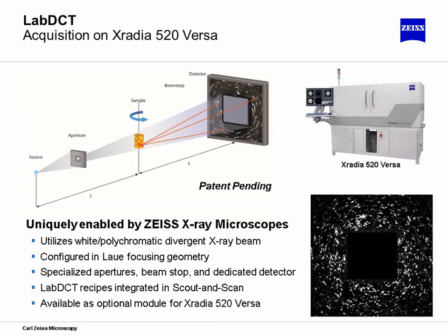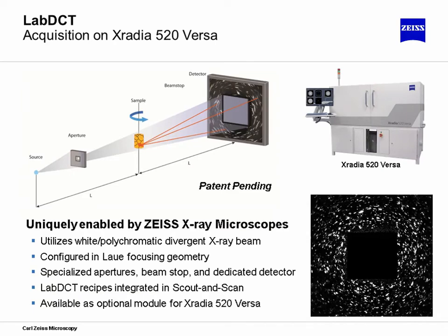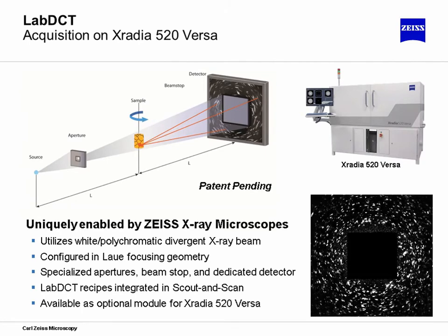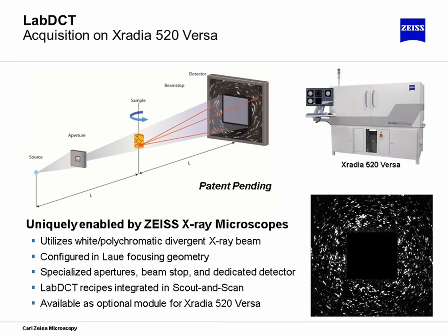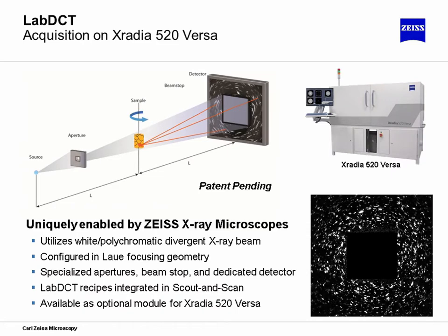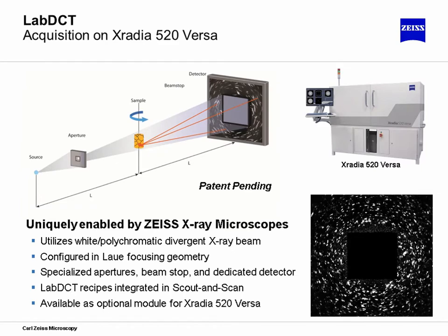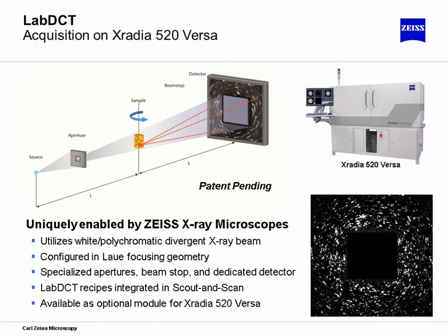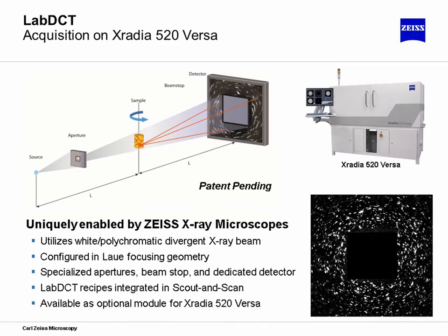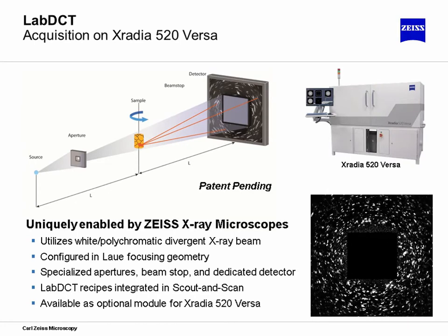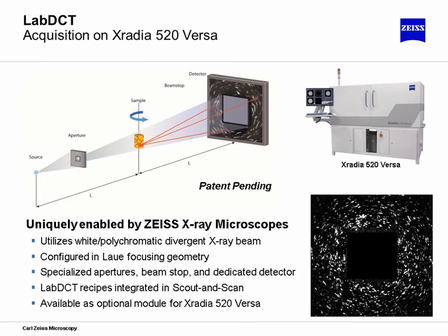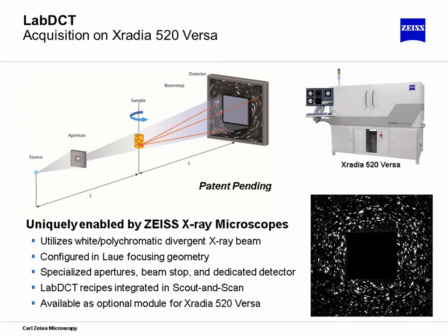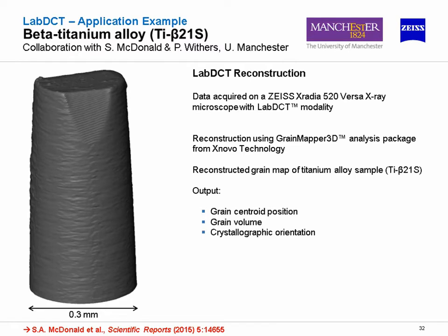Moving along, this shows a bit of the architecture. I don't have time to get into detail of this today, but an aperture is utilized here with a specialized detector where a number of different diffraction patterns are acquired and then reconstructed using reconstruction algorithms developed jointly with our partners at XNovo Technology to reconstruct this crystallographic data, and these are Laue patterns, into a data set that gives you the three-dimensional, non-destructive grain orientation information.